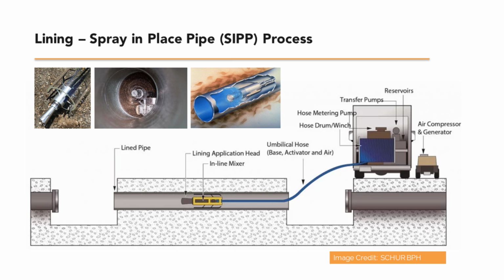The schematic below shows the lining head being towed from a launch pit at left to the retrieve pit at right, as the lining head, shown in the upper left, applies a coating to the pipe wall while it's being winched backwards towards the lining truck. Automated control over winch speed and flow rate provides a uniform thickness of coating within the pipe.